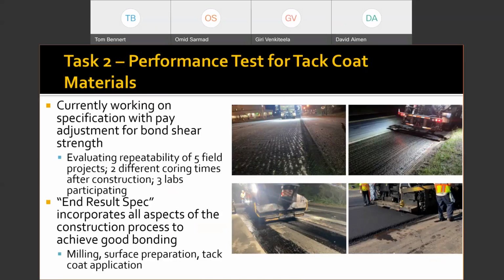And in this case, over on the bottom left, you can see areas that are bare, and this has been picked up by construction trucks. Basically, what ends up happening is the tack gets stuck on their tires and they start tracking it down the road. Obviously not very good. And on the bottom one, you see this little brown, watery looking material out here. What that is, is tack that hasn't broken yet.